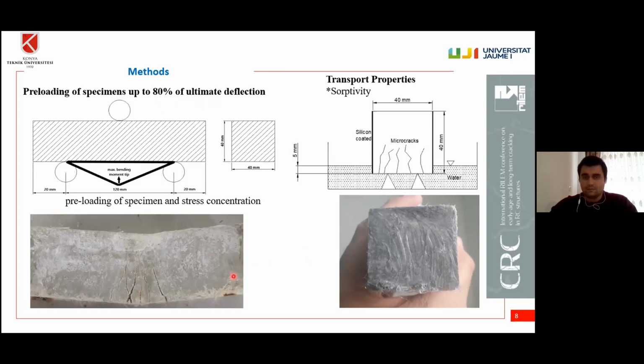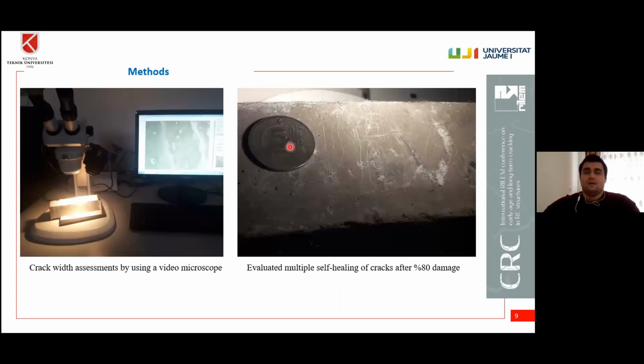After we obtained these specimens, we coated two sides of the specimens with silicone, and then we used the sorptivity test for the evaluation of autogenous self-healing. Besides the sorptivity test, we also characterized the microcracks of the specimens. These assessments comprise the crack width and crack number. As you see, first we defined the cracks, then you can also see the self-healing of the multiple cracks.